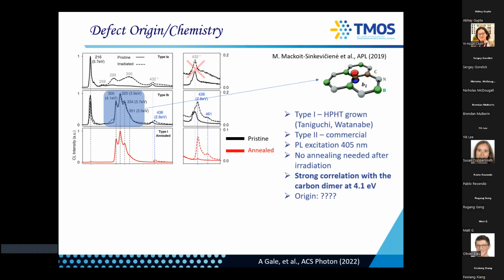Okay, so now let's take another type of HBN, which is very bad. You see there is almost no exciton emission, very defective HBN, and that has a lot of carbon. You see the emission here is very strong. And we can irradiate this and again create these 436 nanometer emitters. Now, we can basically take any HBN, if you anneal them, you would get this carbon defect. So the annealing here is happening before we irradiate with our electron beam. Yeah, before, not after. After, no annealing.